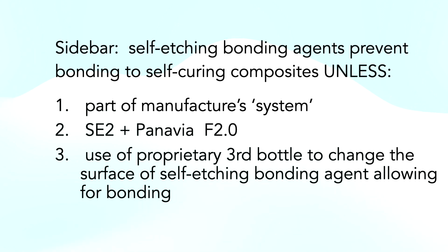Does that make sense? Let me say that again, because it takes a while for new neuron pathways to generate. So you always have an oxygen-inhibited layer on any of these materials, right? So the oxygen-inhibited layer of self-etching systems inhibits the polymerization and attachment of a dual-cure material on top of it. Not a flowable composite, not paste composite, but a dual-cure material, which is what buildup is. And then the exceptions are with Panavia and MDP and a product that Ray Bertolotti invented called Bulk EZ. That bonds to anything. So next year, the lecture's on Bulk EZ because it's the miracle flowable composite.